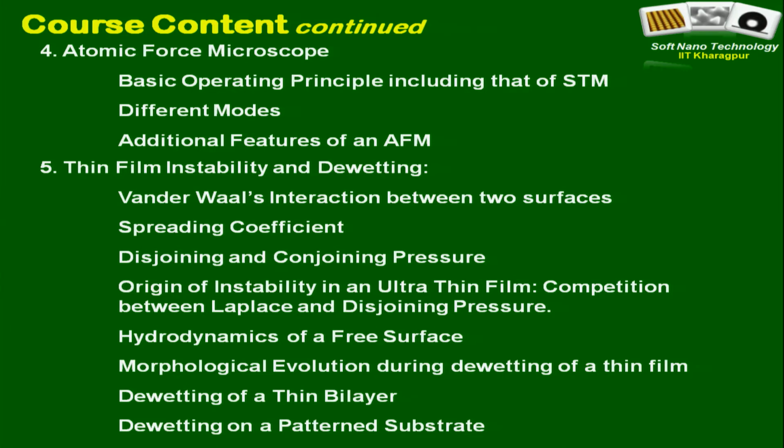So here is a quick word of caution. If somebody asks you what is an ultra thin film, please do not commit any number. The way we have defined it, ultra thin film is a film where you have active van der Waals interaction or non-zero disjoining pressure between the two interfaces. Kindly go through the lecture notes to get an idea about these, and there we realize that on a non-wettable surface particularly, one can correlate it to the sign of the Hamaker constant or the magnitude of the disjoining pressure, right.